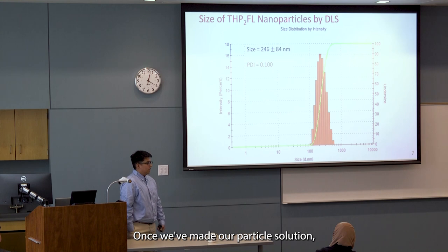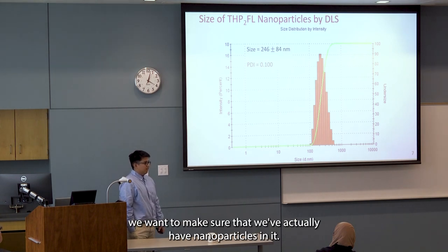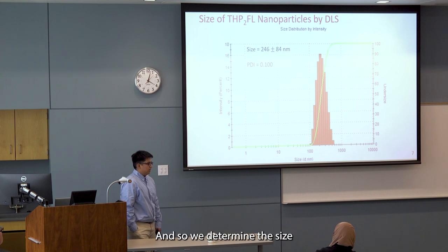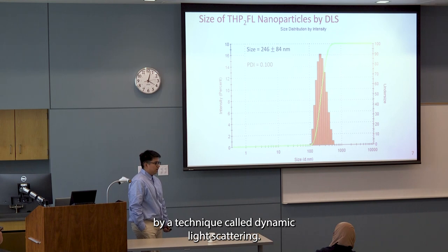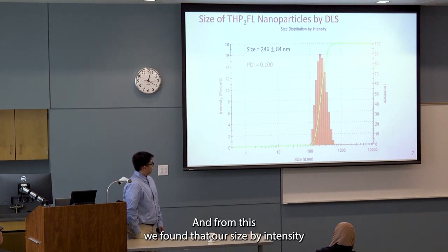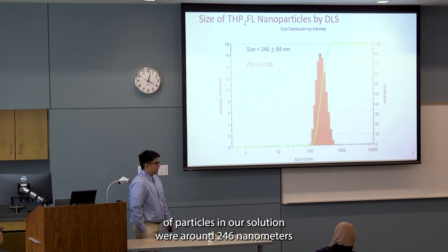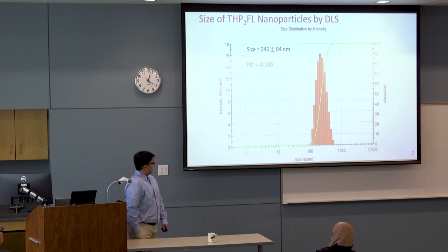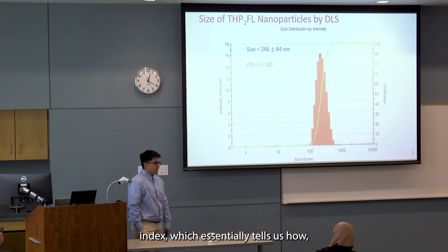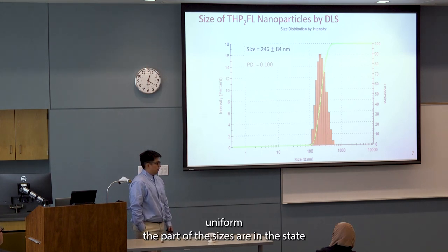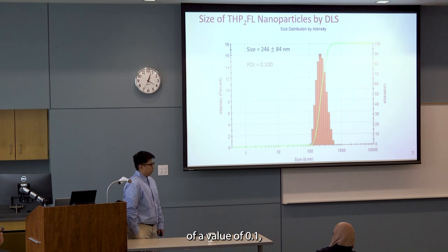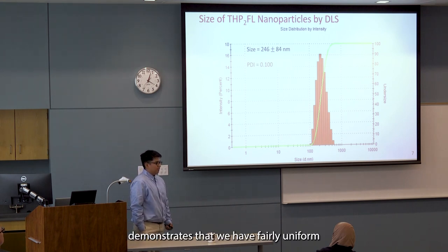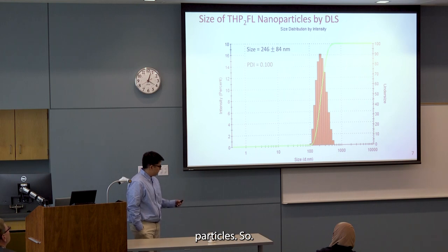Once we've made our nanoparticle solution, we want to make sure that we actually have nanoparticles in it. And so we determine the size by a technique called dynamic light scattering. And from this, we found that the size by intensity of particles in our solution was around 246 nanometers. And the PDI, polydispersity index, essentially tells us how uniform the particle sizes are within our sample. And a value of 0.1 demonstrates that we have fairly uniform particle size.